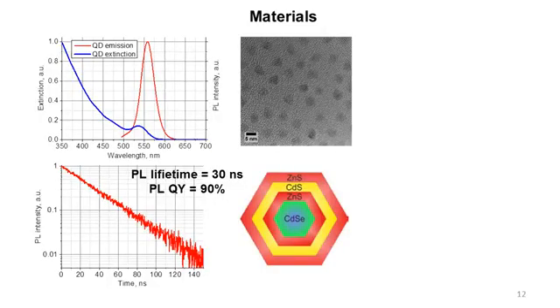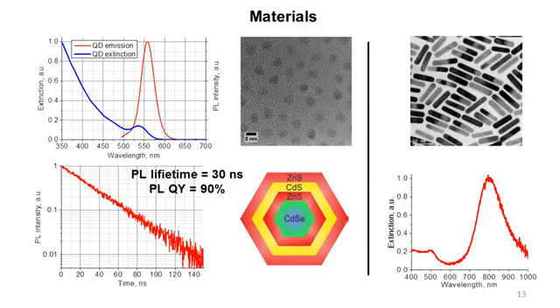For experiments, we use semiconductor quantum dots with multi-layer shell. Quantum dots consist of cadmium selenide core and 3 monolayers of zinc sulfide, cadmium sulfide, and finally zinc sulfide. The diameter of used quantum dots was about 4.5 nanometers. The maximum of the photoluminescence spectrum was at 560 nanometers, with full width at half maximum of 35 to 40 nanometers. The photoluminescence quantum yield of used quantum dots was 90% in the hexane solution, and corresponding photoluminescence lifetime was 30 nanoseconds. In some experiments we used gold nanorods.